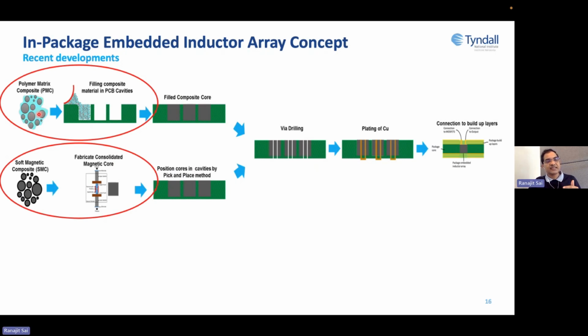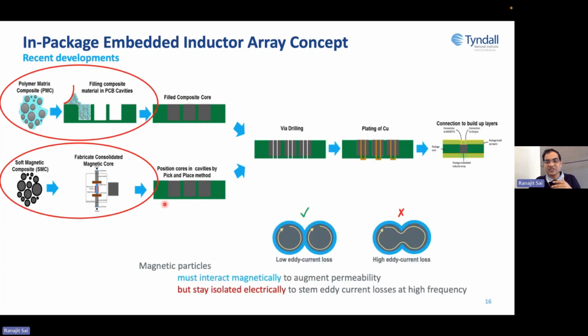That permeability of 8 can come down to 1 or 2 very easily if your engineering of this material is not good enough. And if you get high permeability, loss can also go very high, because the objective is to have low eddy current loss so that two particles are not touching. If they are too far away, loss will be low, permeability will also be low. But if they are touching, then permeability will be high, loss will also be high. So we have to make a balance, and that's where the surface engineering comes into the picture, and a lot of research is required in this particular area, how to make this composite core appropriately.